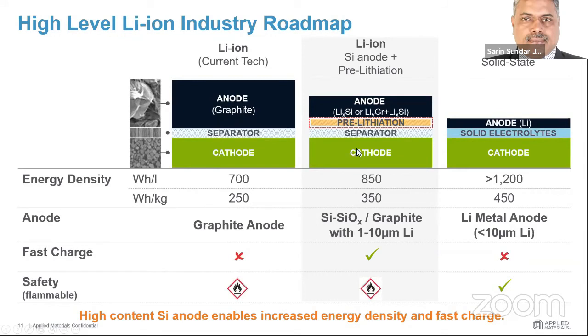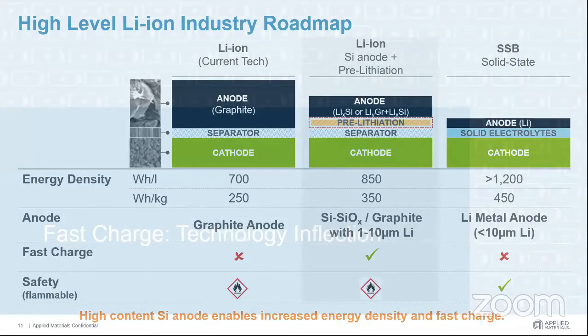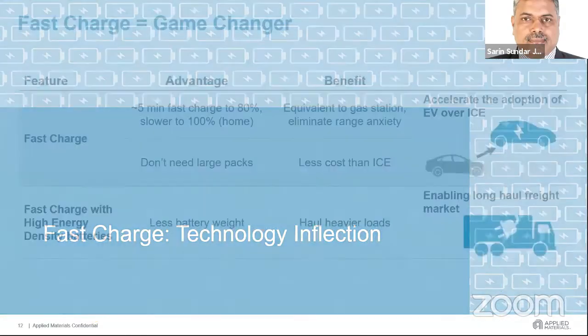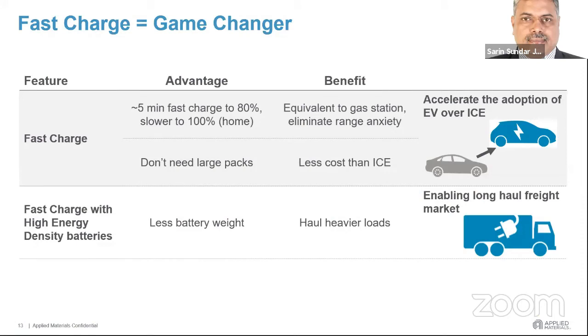And this will basically improve the energy density per kg. And this can be used for existing battery technologies just by increasing the anode side. So we heard Professor Murugan talk about the separator, and also metal-air and metal anode-free batteries for the future. And we already have technologies right now on the anode side. We can deposit pure lithium metal on copper foils at very, very high speeds at a cost that is actually less than what the industry currently uses for the anode cost. And where we are at fast charge, typically we want to charge in less than 5 minutes, because that's the time that we wanted to use.